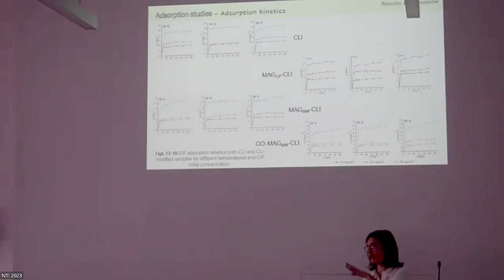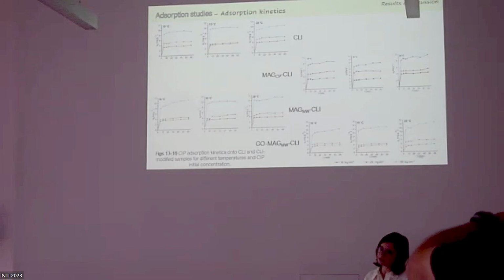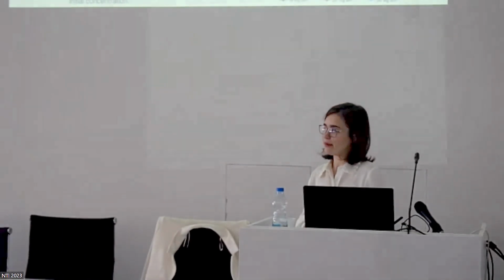Okay, first I dry it in so absorption, then drying, then plasma, but still, since it is zeolite, there is moisture in the air. So yes, the content of water or moisture in the sample can affect the plasma chemistry, because when plasma comes in contact with water molecules, novel oxygen and nitrogen species are formed that can make a richer plasma environment, and then help to degrade or clean the zeolite surface.